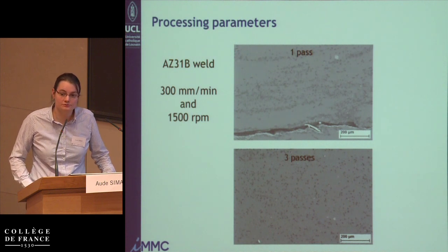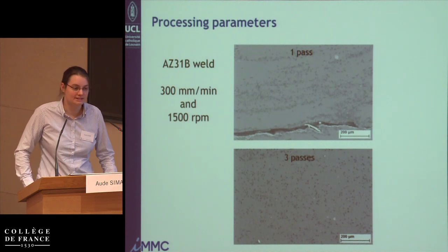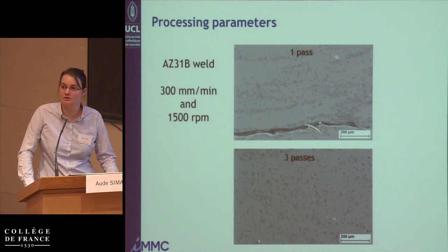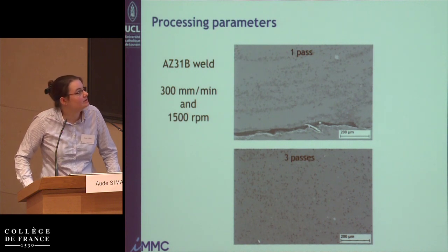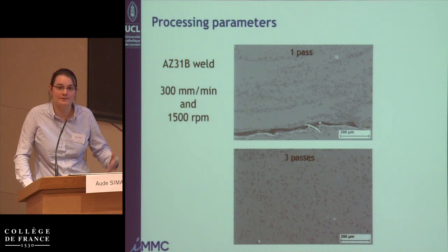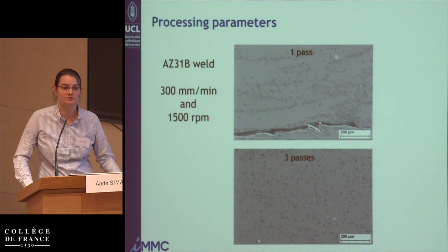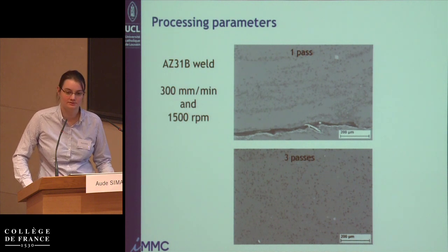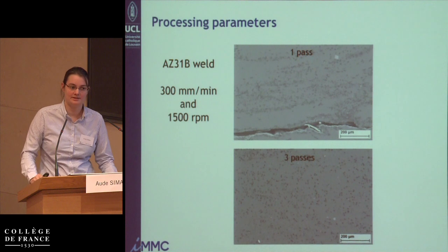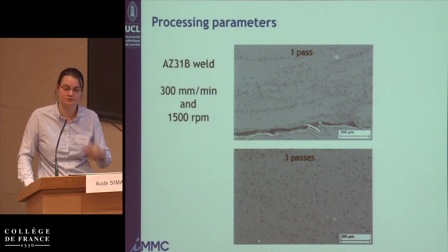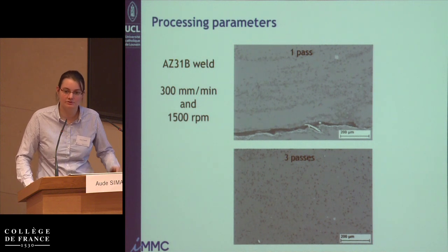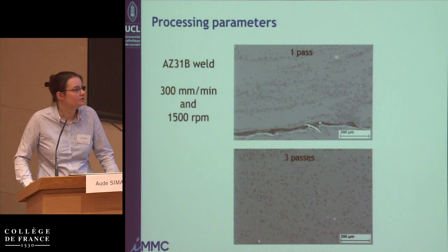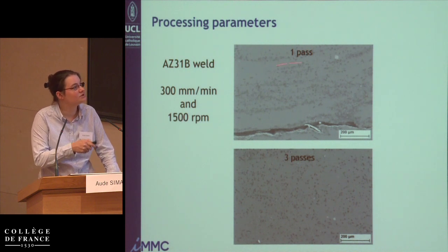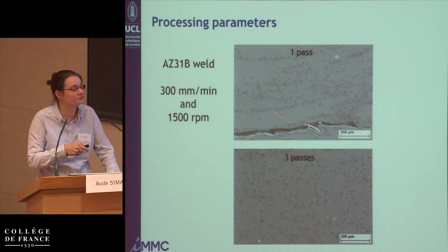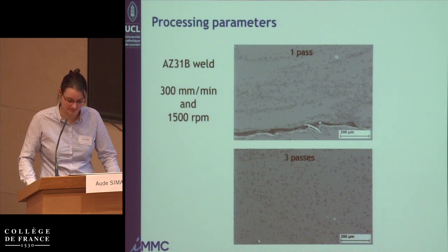Also, we had to do successive passes, like we did in the copper application, because after only one pass, all the defects, the holes that were present in the overlapping carbon fabric still had some holes in between, and so all that was not completely closed after one pass, so we had to input many passes. And also you see the distribution after one pass is not that good. You still have regions where you only have magnesium matrix.